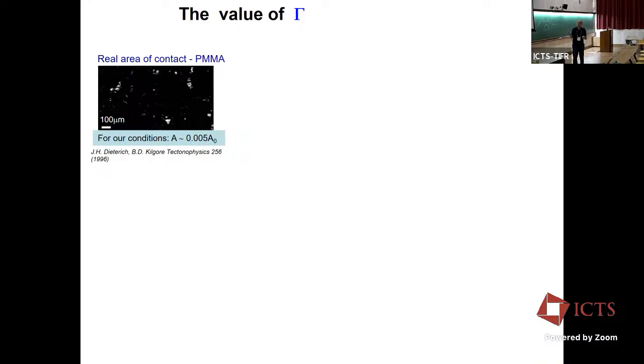I won't talk about it, but one can take this value of gamma and then say what should be the temperature rise at the instant. I know how thick the layer of the interface is. It's about a micron thick. So I can throw it in there, and then you get a large temperature rise of the contacts. We had this discussion over lunch a few days ago, but this is happening so fast, I'm not sure there's a real concept of temperature here, because it's such a non-equilibrium phenomenon that you don't populate all of the degrees of freedom if you have a disturbance moving at the sound speed. But you can see how much heat per unit area you get at the contacts, but I won't be talking about that here.